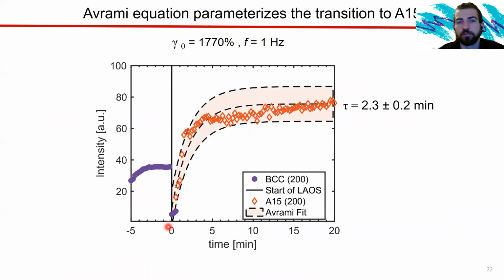Okay, so here's the intensity versus time data for that first experiment video I showed you. After the thermal annealing procedure, we have BCC at time equals 0. We start shear. A15 comes screaming in, and you can see that our Avrami fit captures a lot of the behavior fairly well. And we have a time scale of about 2.3 minutes for the A15 formation to take place.